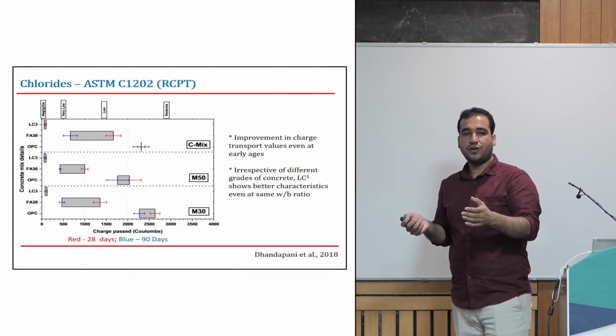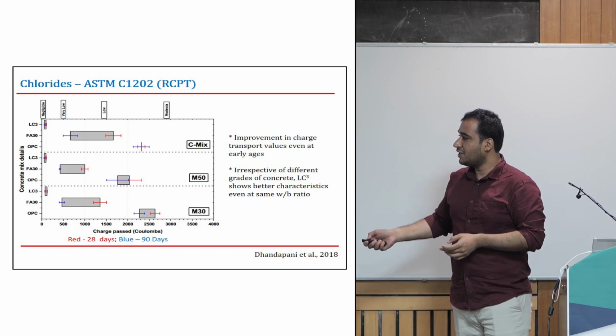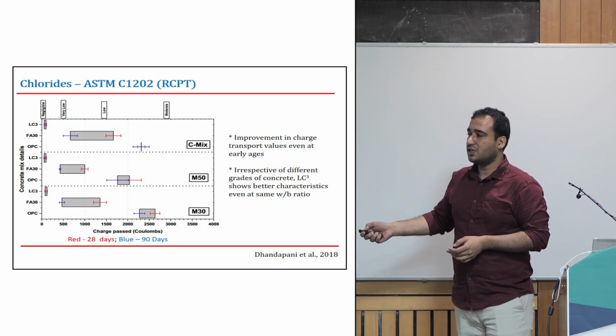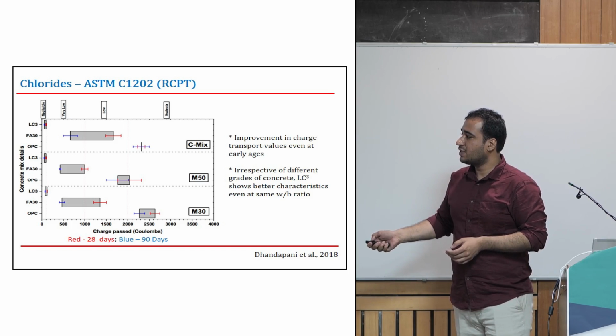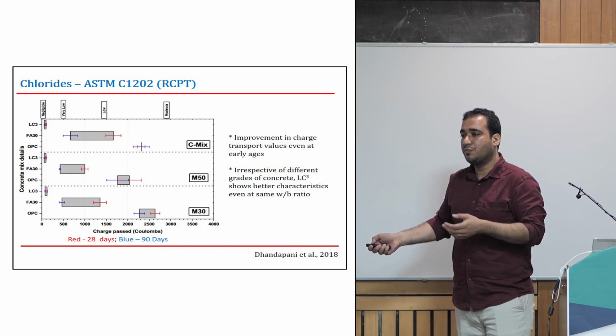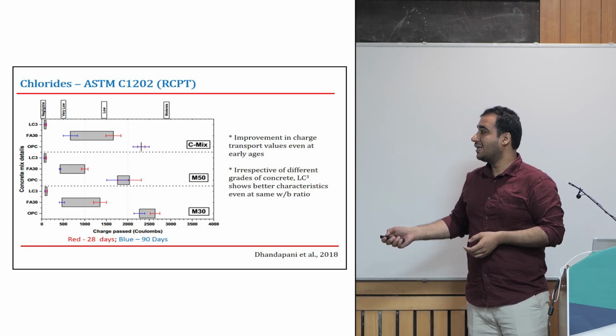In LC3, this pore refinement happens quite fast. So even at 28 days, you see the charge values are negligible. But for other cases like fly ash, after 90 days you start seeing an improvement. But then again, it's not as good as LC3.